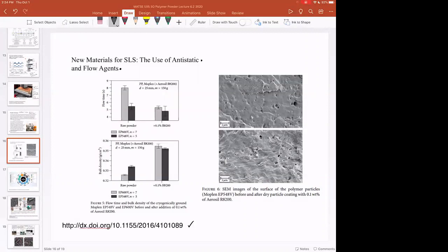And so this is just a nice study showing that they're going to add 0.1% of this Aerosil R8200. So this is a flow agent. And basically this helps polymer powder flow better. That's why it's called a flow agent. And so you can see the flow time for a certain measurement they're going to make goes way down, which means that this will flow more easily. And also this bulk density goes up. And so if the polymer is flowing more easily, the bulk density increases. And so that can help with sintering.